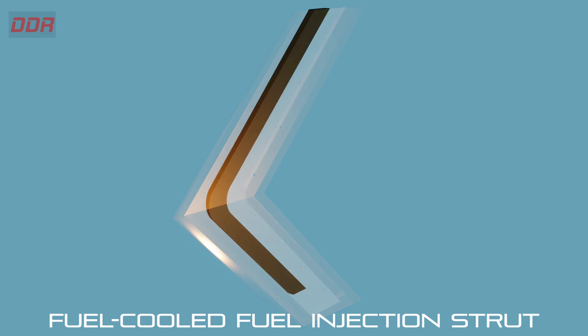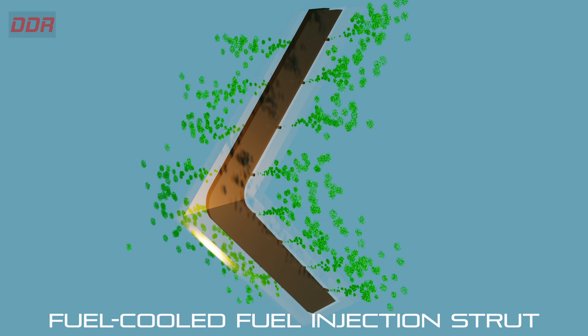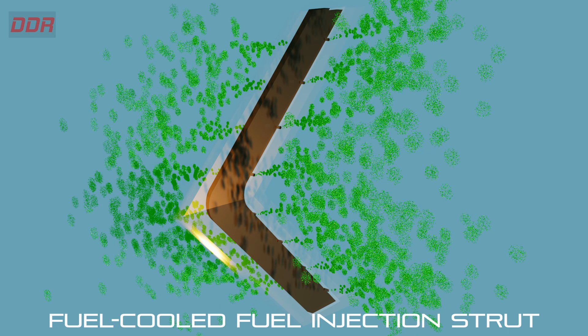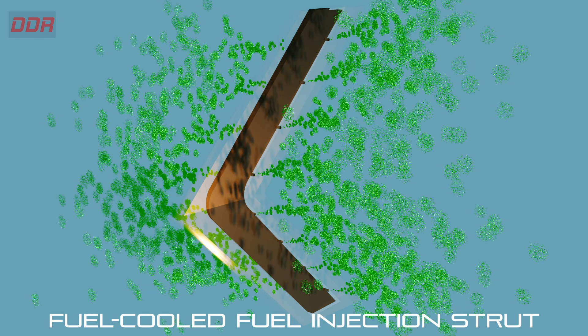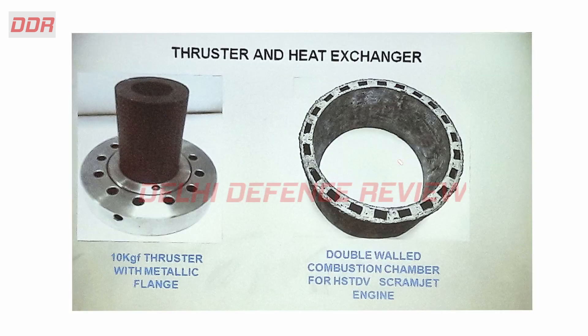Formation of a thin layer of zirconium oxide with very high hardness prevents further oxidation and erosion, making zirconium composites a seemingly better candidate than silicon carbide or carbon composites for sharp-edge features of hypersonic vehicles. Fuel-cooled injection struts are being used to tackle intense heating. There is ongoing research in the U.S. and China on using transpiration cooling from leading edges to further lower heat flux. Silicon carbide-based struts have been manufactured for a scramjet combustor, as has a silicon carbide composite double-wall scramjet combustor. We'll know the results of these development programs when they are released for public consumption.